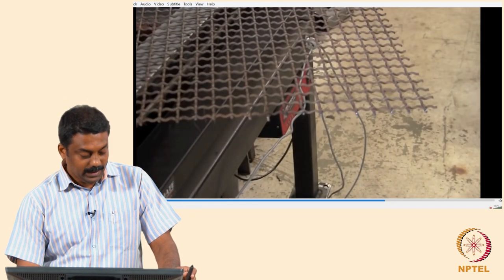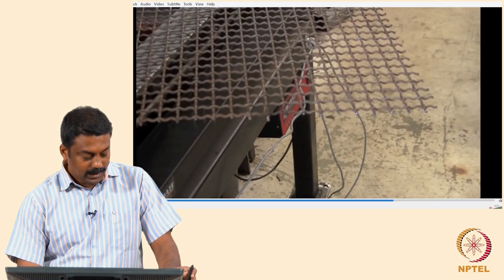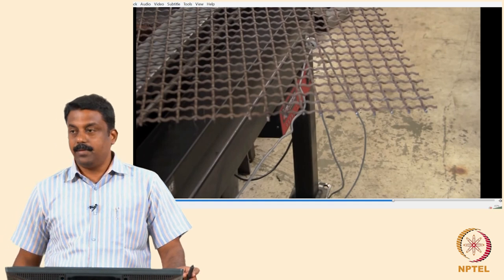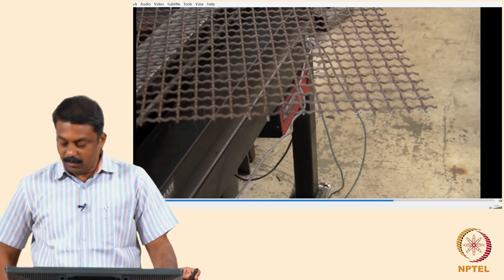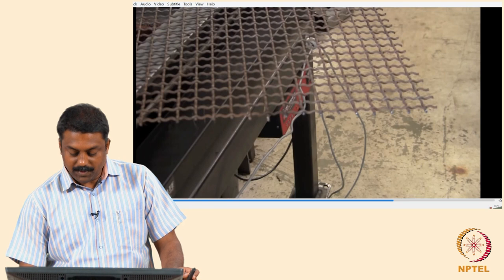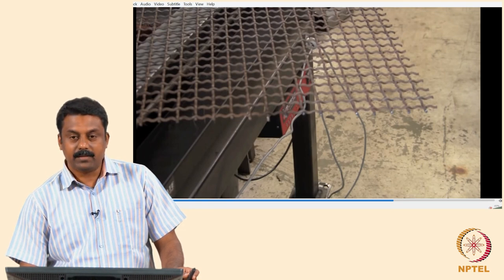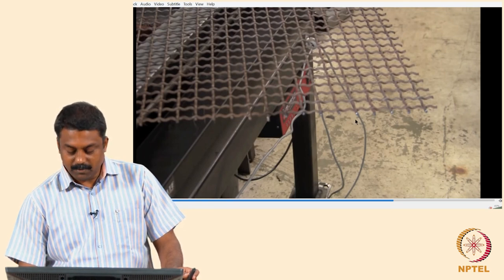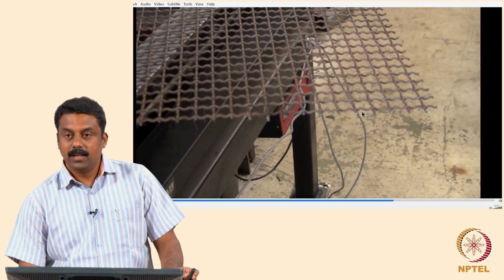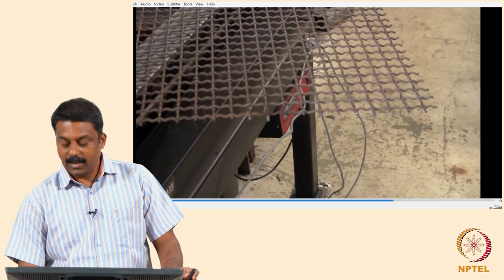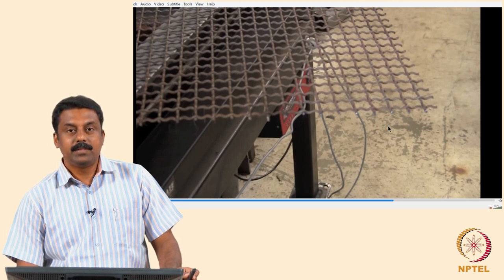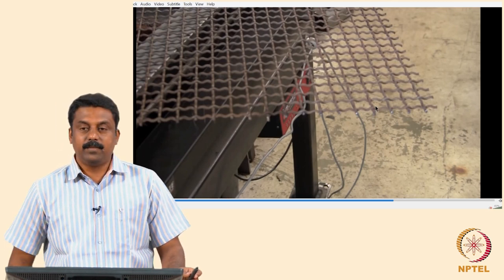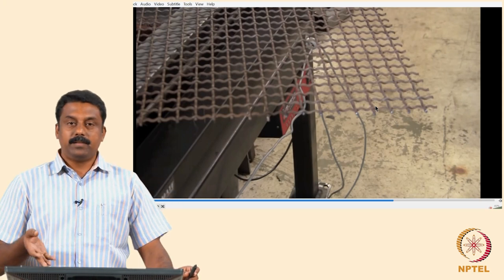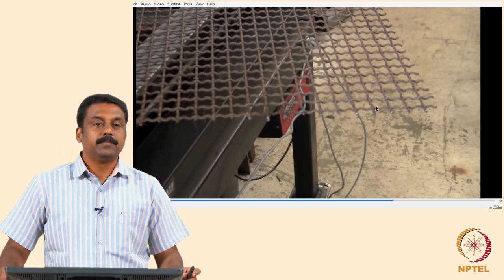So these kinds of cutting applications are very handy, and similarly you can also play around with the heat input when you are welding subsequently. Suppose you want to cut and then attach another sheet simultaneously. So you cut it out and then use a pilot arc to weld, and then use a transferred arc to cut and pilot arc to weld, and sequentially you do it. So it gives a lot of flexibility in terms of handling complex systems like this mesh.